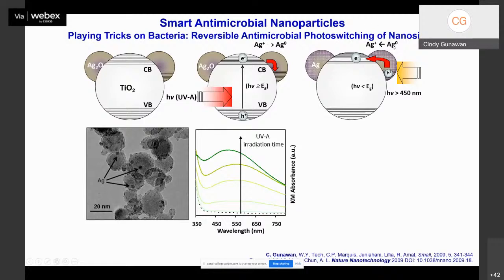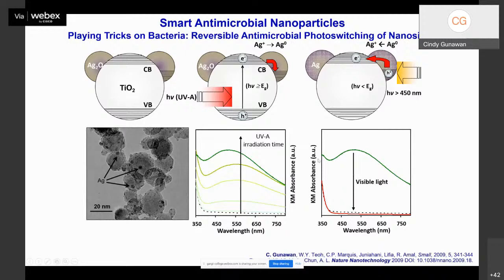And we know that metallic silver, because of its surface plasmon resonance, will now be responsive to visible light, of wavelength higher than 450 nanometers. So upon irradiation of these particles with visible light, because you already have the metallic silver deposits in the particles, there will be a reverse electron flow from the silver deposits to the titanium dioxide, and in turn the metallic silver is oxidized back to silver 1. And to confirm this, with the visible light illumination, we could see the disappearance of surface plasmon resonance. It means that the metallic silver here has been oxidized back to silver 1.